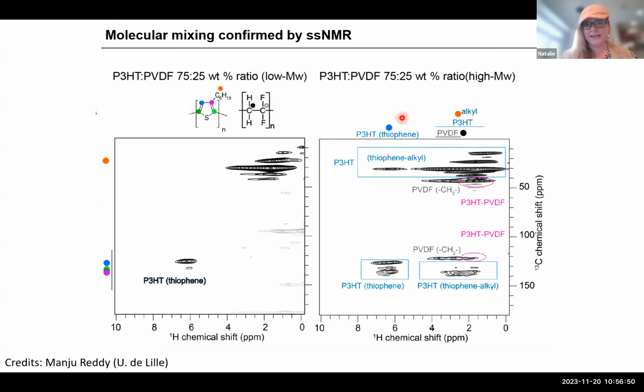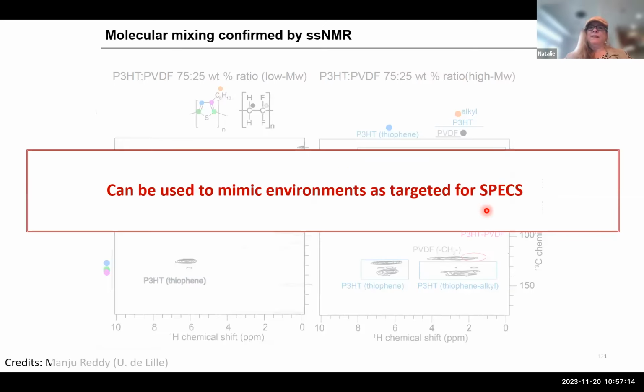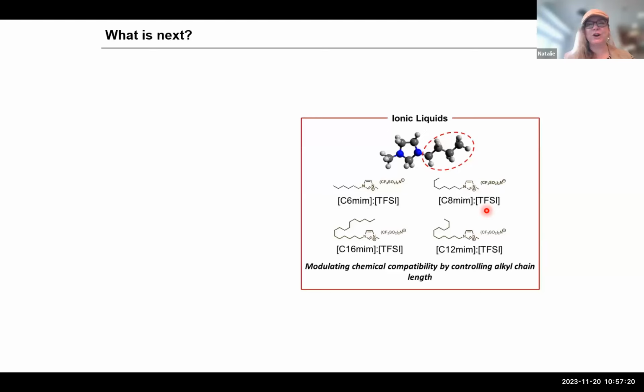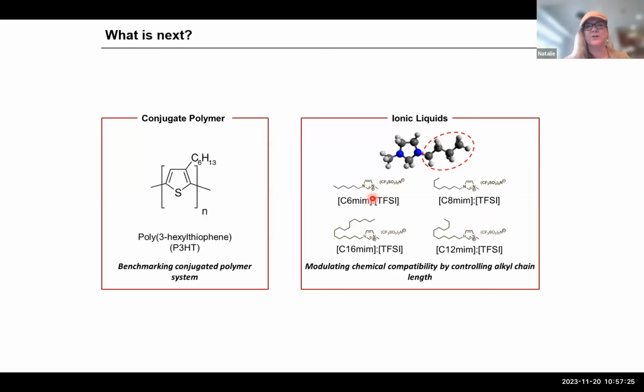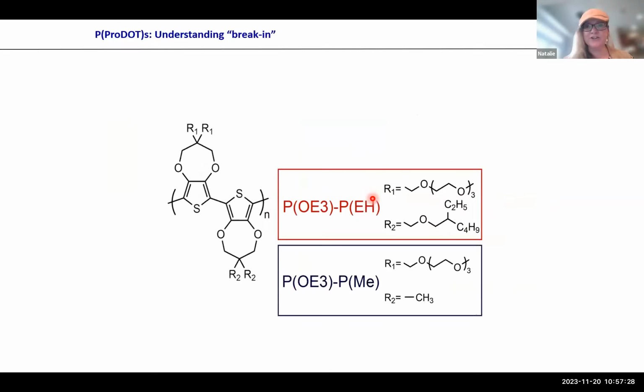I will not go into detail here, but I can show even with 2D NMR, done with Manju Reddy in Lille, when you compare the P3HT with the blend, there are new interactions, new signals in 2D NMR. And they show that we have very close interactions between P3HT and PVDF. So we can mimic, at least to a certain extent, the environment as in a liquid electrolyte. And again, here we continue blending using, rather than PVDF, ionic liquids, etc., where we saw similar things. But with that, I think I should end.